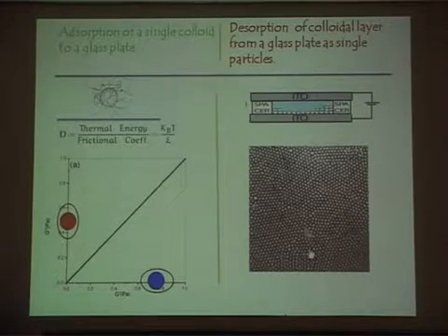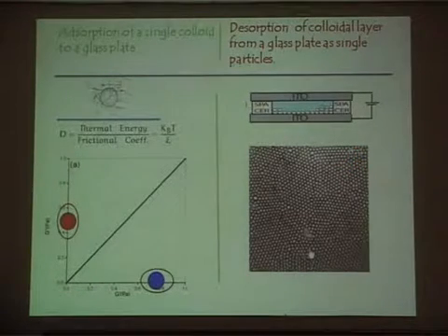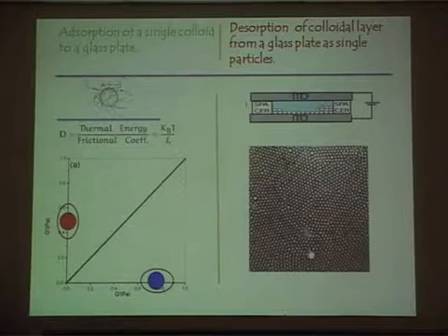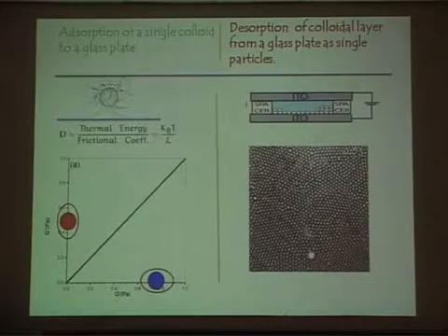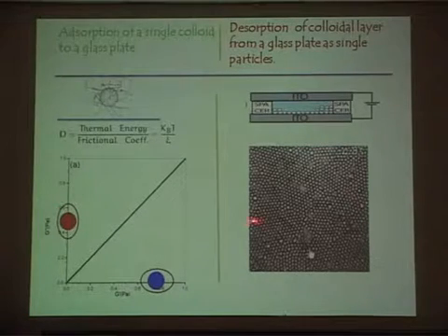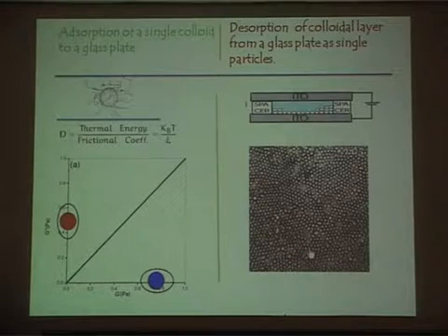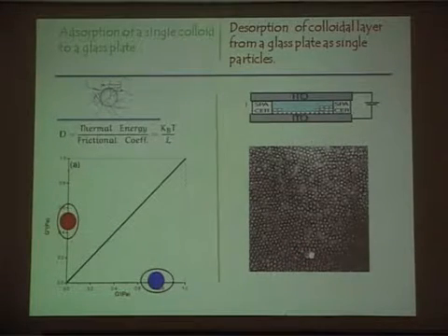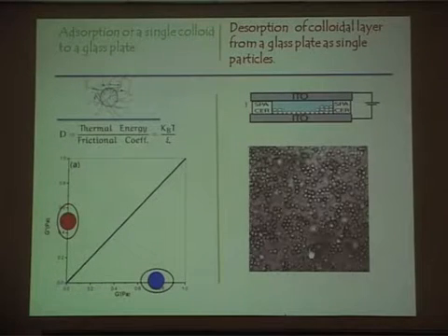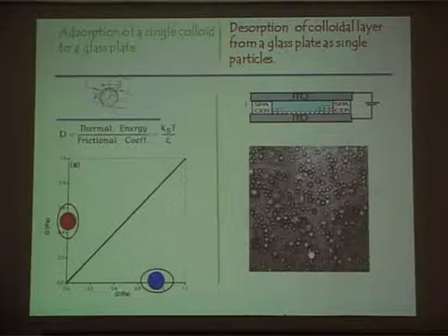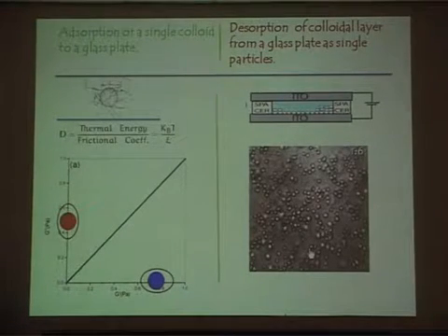So as I apply the electric field, in terms of voltage per 100 microns, I start seeing individual events. There will be particles which start popping out of the plate. This particle, the other particles have gone out of focus, I'm just imaging one plane. So this is an event where I see desorption, and the length scale is a single particle event.